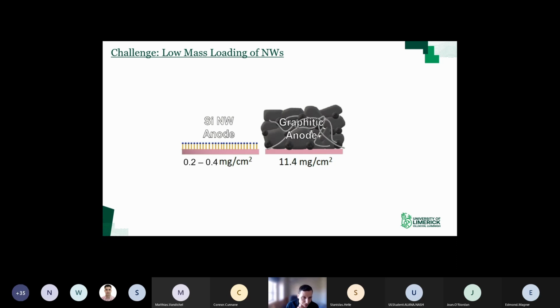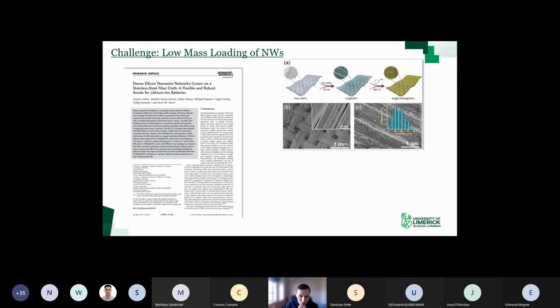Whereas if you look in the literature, the typical mass loading of directly grown nanowires is much lower than that. So it's about 0.2 to 0.4 milligrams per centimeter squared. So that's clearly an issue if you want to commercialize silicon. So we just published a paper in Advanced Materials. Sumer was the first author on this, tackling this problem basically. So looking at, can we increase the mass loading by using different types of current collectors, and also can we increase the flexibility, which is important if you want a flexible battery.